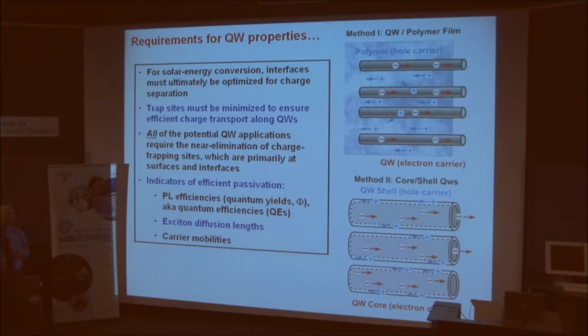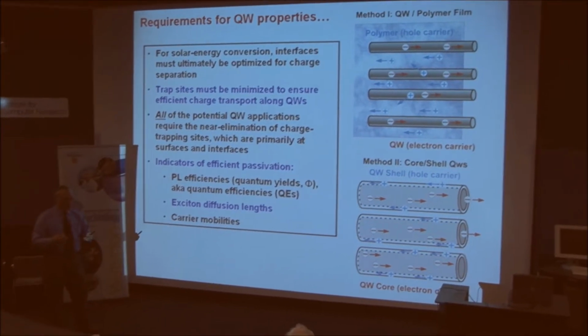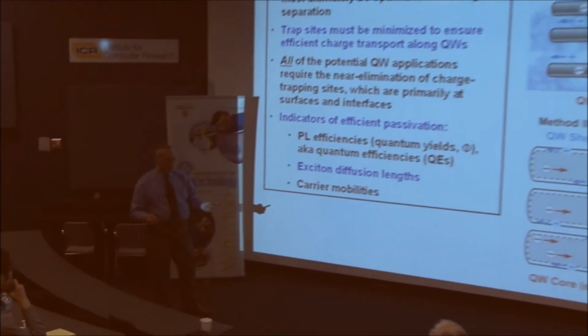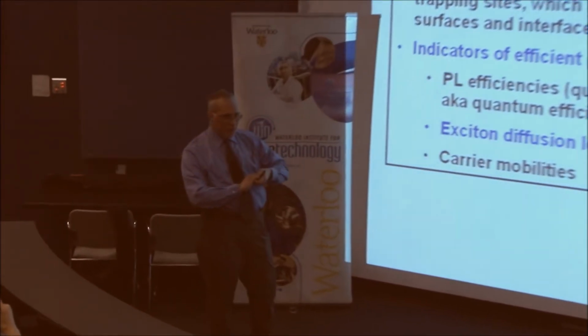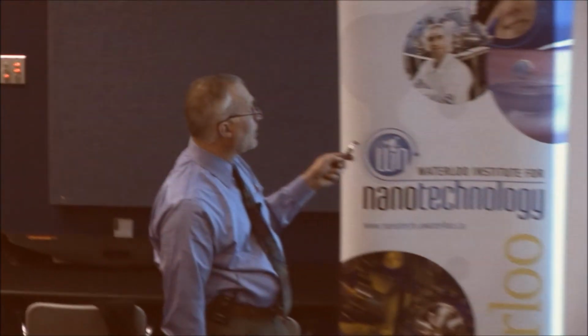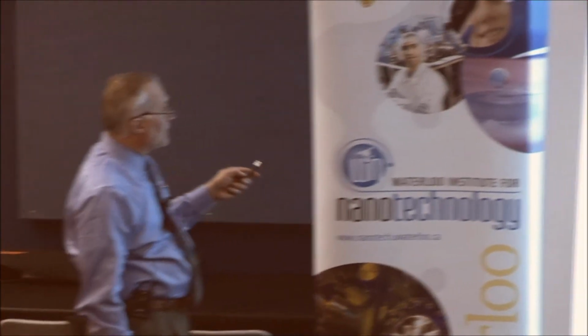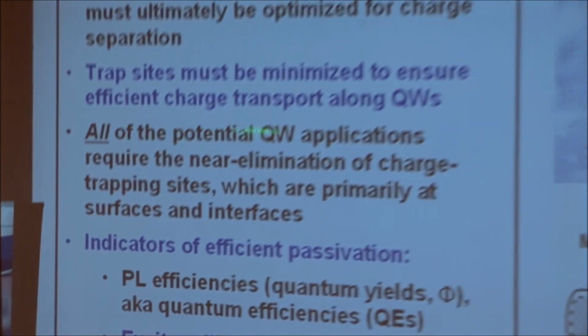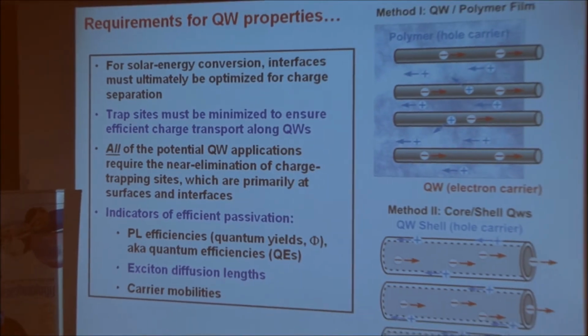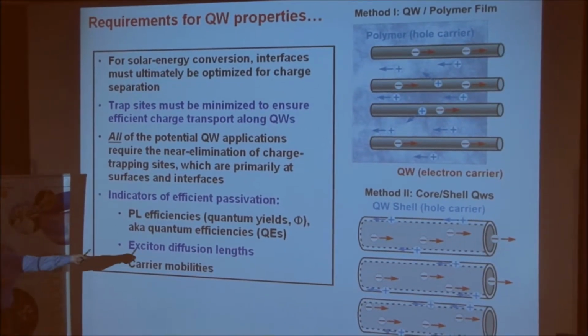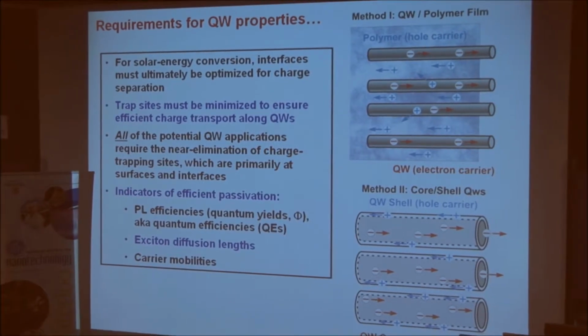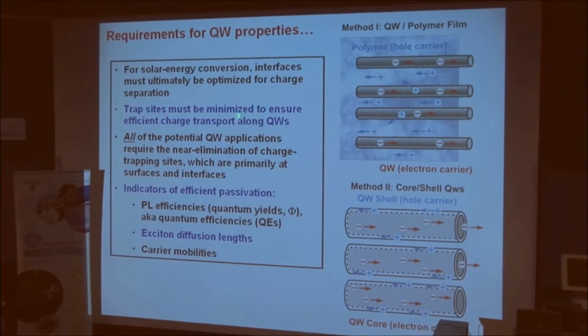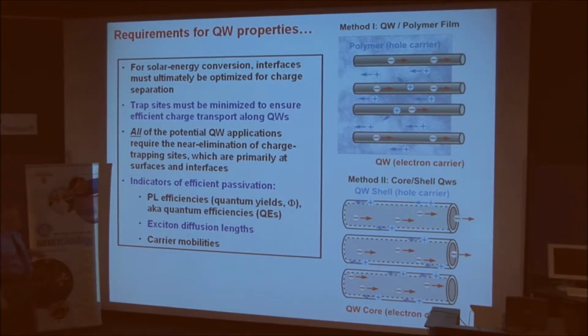Let me just make one point explicitly clear here. I seem to be very committed to photoluminescence efficiencies, which is actually the radiative recombination of electron-hole pairs, whereas certain applications, like solar energy conversion, focus not on the recombination, but on the separation of electron-hole pairs. But one thing is certain, that all of the potential quantum wire applications will require transport of charges, charge carriers, or excitons along the long axis of the wire. And in order for that to happen, trap sites must be minimized. That allows efficient charge transport.